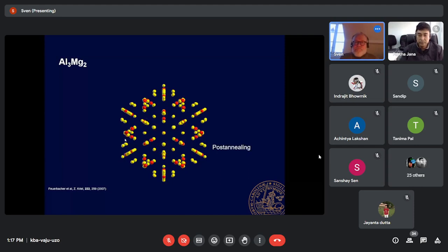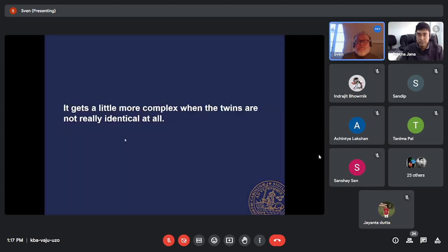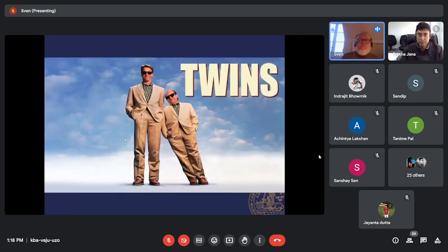Still, what we are looking at here is a twin. It's a rhombohedral twin of 4 individuals. So in order to solve the structure, you need to know that it's a twin, and you need to treat that twin. And there are technical tricks for that, but you have to remember to look for these possibilities, because sometimes the problem that you have with poor data is that you've got twinning. Now, sometimes things are a little bit worse because it's twinning with different crystal structures.